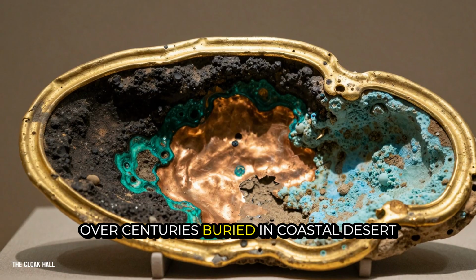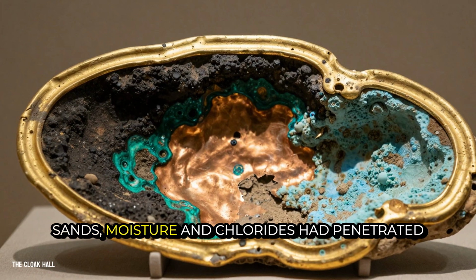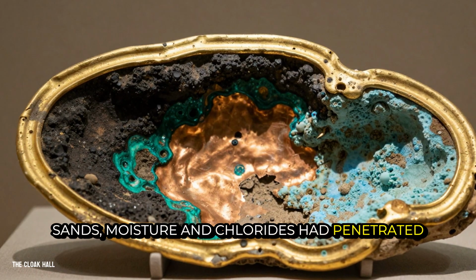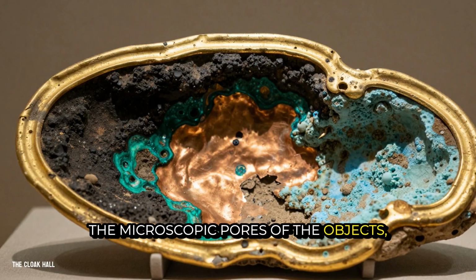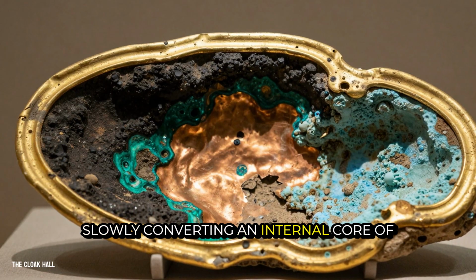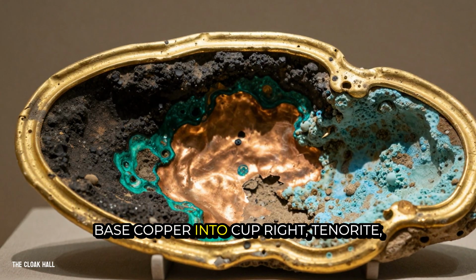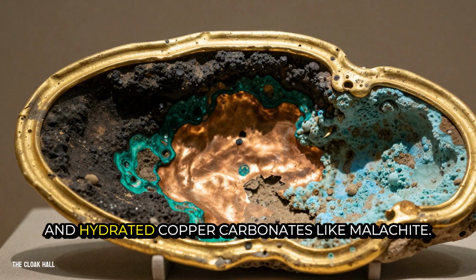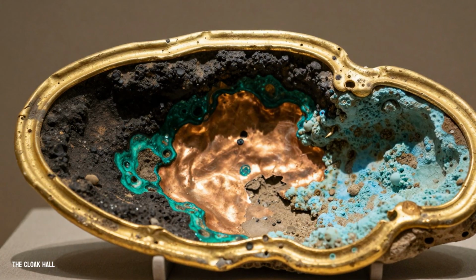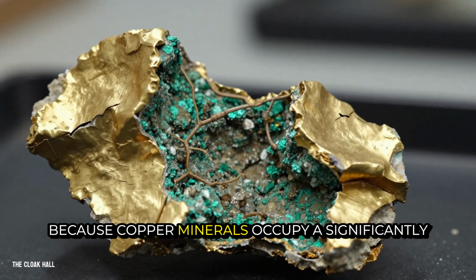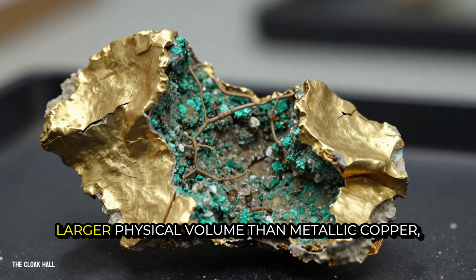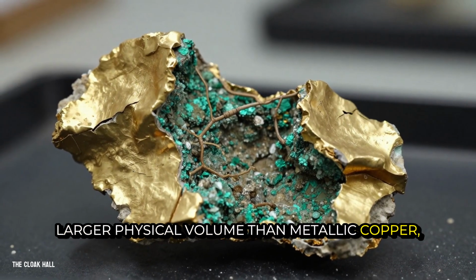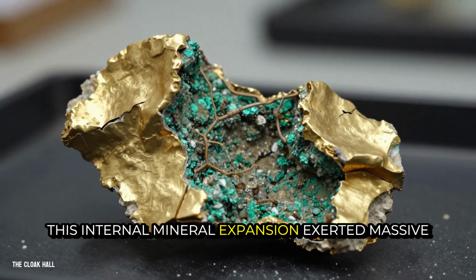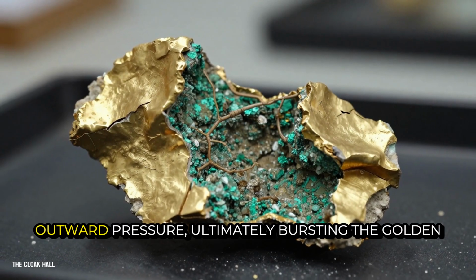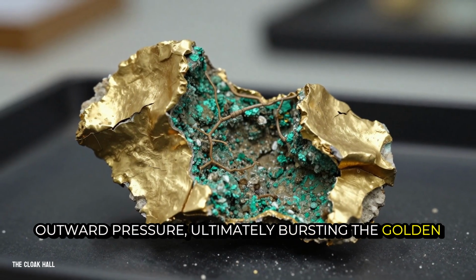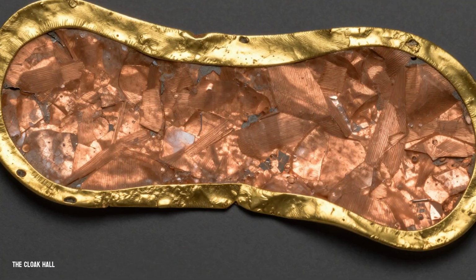Over centuries buried in coastal desert sands, moisture and chlorides had penetrated the microscopic pores of the objects, slowly converting an internal core of base copper into cuprite, tenorite, and hydrated copper carbonates like malachite. Because copper minerals occupy a significantly larger physical volume than metallic copper, this internal mineral expansion exerted massive outward pressure, ultimately bursting the golden exterior from the inside.